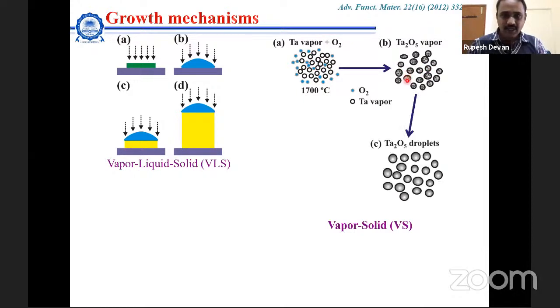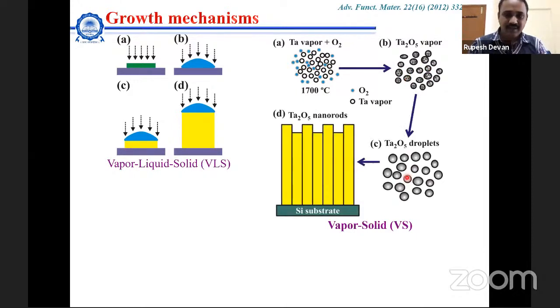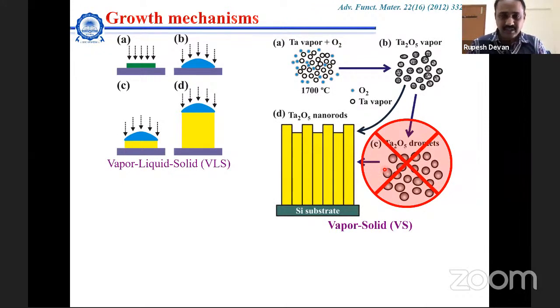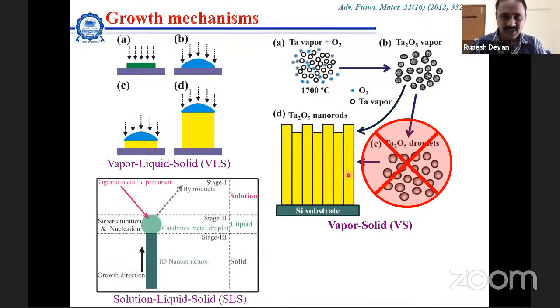Then rather than converting into droplets, you can directly convert these droplets to nanomaterials, which was what was happening in VLS growth mechanism. You can stop conversion of these droplets from vapor, and then you can directly move to the one-dimensional growth. So here you can avoid the capturing of the foreign particles inside this structure.